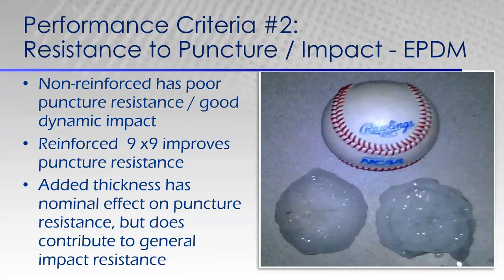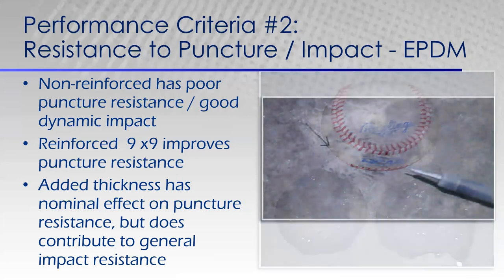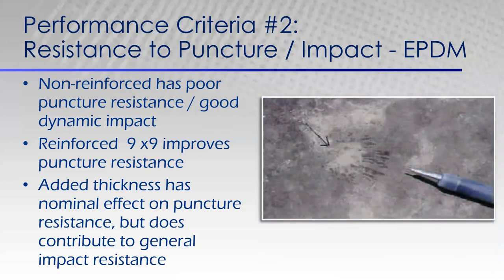So as we mentioned, some of the thicknesses of EPDM can go up to 120 mil thick. The added thickness contributes to that general impact resistance, but it has absolutely no bearing or very minimal bearing on the puncture resistance of this membrane on the roof. You can see here baseball size hailstones. Also here, you can see a scuff mark on the roof. And while it might appear that it was just a scuff mark, it really doesn't have much impact on it